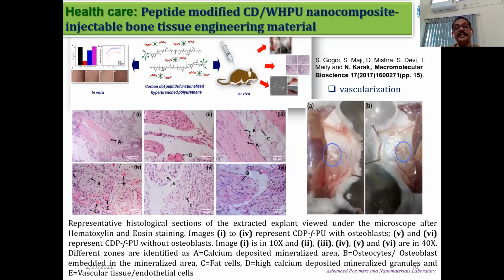But we thought that this surgery is a painful phenomenon, so patients suffer a lot. Can we do regeneration of bone by using an injectable polymer nanocomposite instead? In a DBT project, we used a peptide modified carbon dot and waterborne hyperbranched polyurethane along with gelatin. With help of biotechnology at IIT Kharagpur, we successfully demonstrated that we can inject this scaffold material, which becomes a gel at body temperature and can be used as a scaffold for bone regeneration. Calcium deposition and other cell formation, osteoblasts and osteocytes, are found after implantation of this injectable bone tissue scaffold.